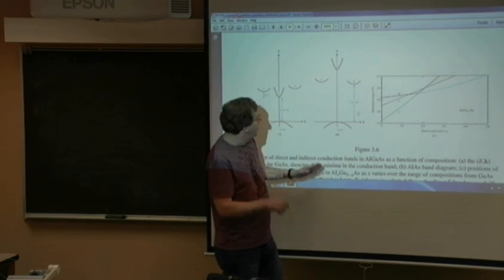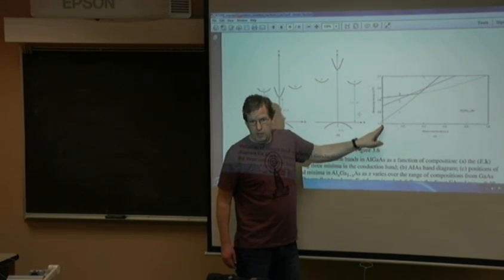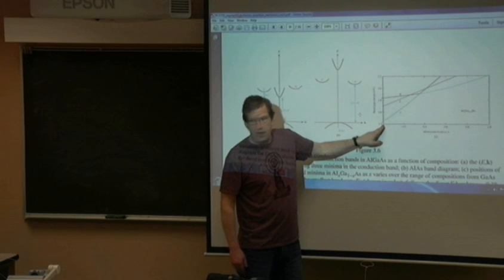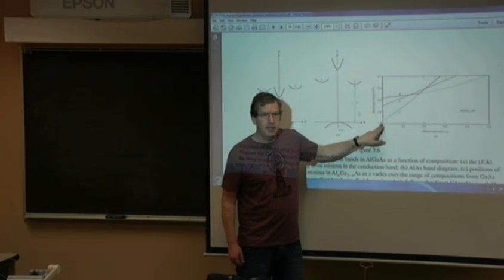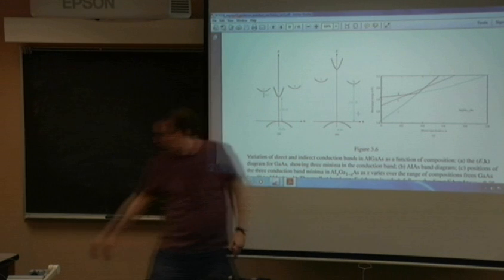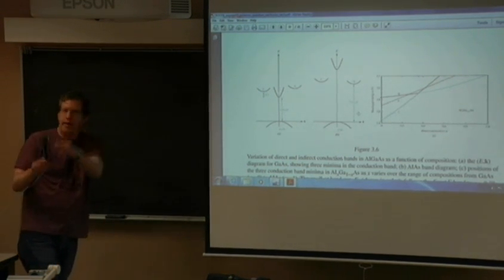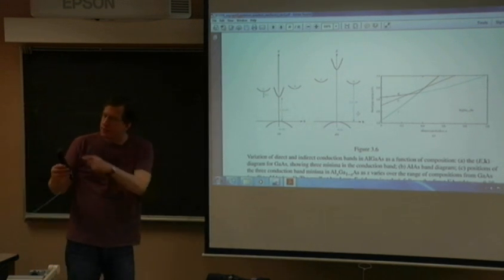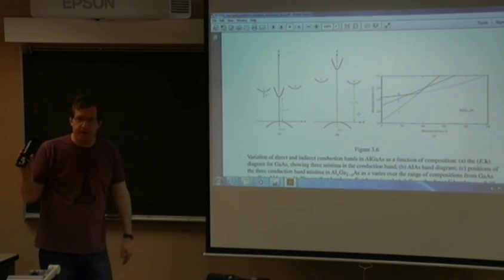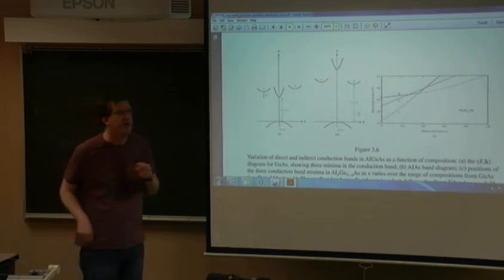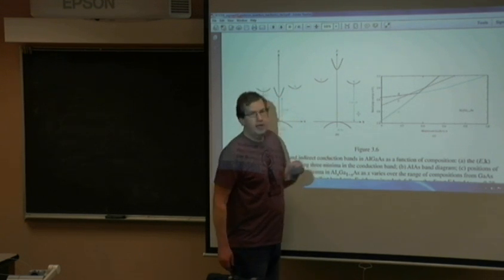So it turns out that's actually a rate limiting step, because aluminum gallium arsenide at 0% aluminum, I got pure gallium arsenide. That's an LED that emits at 850 nanometers. That's probably this remote control here. It's talking to that camera. I didn't realize it was on the wire. But there's probably a gallium arsenide LED in there. And it emits at 850 nanometers. And since your eye only goes to a little beyond 750, your eye is unable to see it.